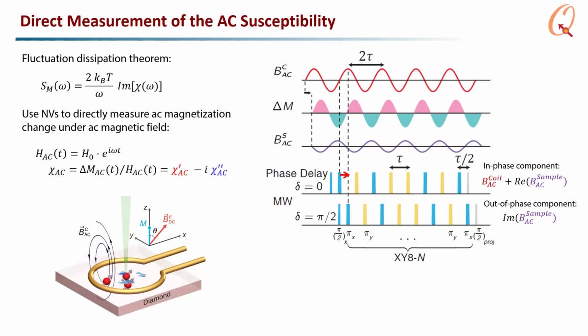One last thing we did is that instead of measuring the spectrum of the noise through relaxation, could you measure the susceptibility directly? Those are related by the fluctuation dissipation theorem, where the spectrum of the noise is related to the imaginary part of the susceptibility. To measure the susceptibility of the magnetization, we have to drive it with an AC magnetic field. So we can just put in an extra coil here, similar to